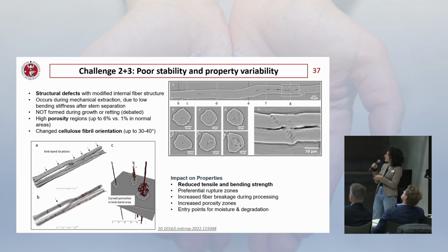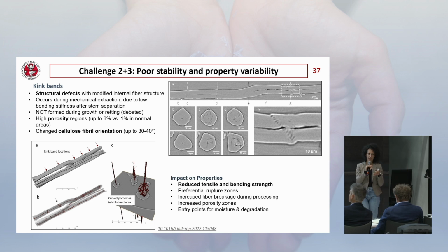The poor stability combined with the property variability is what is observed here in the slide instead: lignocellulosic fibers also have the so-called kink bands. The kink bands are these folds over here in which you have an increased porosity, and they, of course, massively decrease the tensile strength of the fibers and also the tensile strength of the final composite.